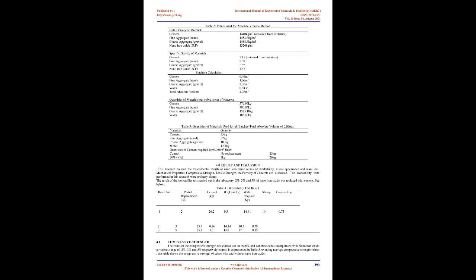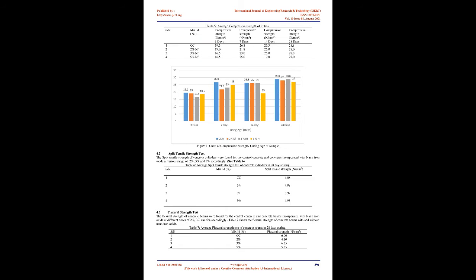Sulfate Concentration, Exposure, and Testing: The specimen was cured for 28 days. The specimens were divided into two groups: the first group of specimens was continuously cured underwater while the second group was placed in the second tank with the sulfate concentration 300g Na2SO4. The exposure condition represents very severe sulfate exposure conditions according to ACI 318-12. Solutions were renewed in periods of 14 days and mass changes were determined at the same periods. The effect of sulfate concentration on the performance of plain and blended cements was evaluated by visual examination and measuring the reduction in compressive strength.